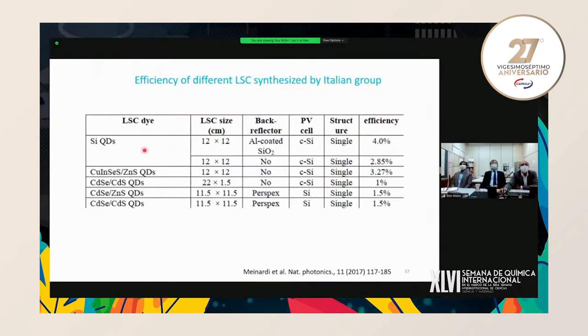Here we can see that not only the luminophore, but there are other components that can increase the efficiency of LSCs, like coating with a back reflector. This is aluminum coated SiO2, and this is without reflector. Here we can see around 4% efficiency with back reflector, and without back reflector, 2.85. And there are other reflectors also, like Perspex. They also increase the efficiency.